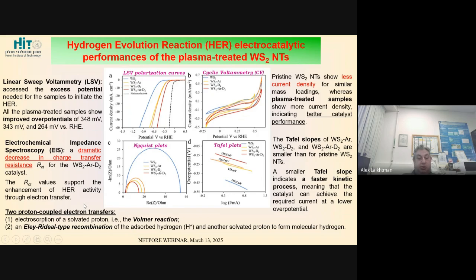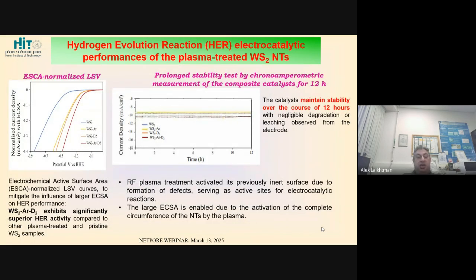So we suggested this kind of mechanism. Again, I'm not an electrochemist, so we should discuss this with my colleagues from Ariel, but they consider that it's electrosorption of a solvated proton, a kind of Volmer reaction, and then recombination of the adsorbed, adsorbed hydrogen and another solvated proton to form molecular hydrogen within this hydrogen evolution reaction. Of course, we performed another test. For example, we also measured the stability of the so produced composites, and for at least 12 hours, there is very negligible degradation of the electrodes.